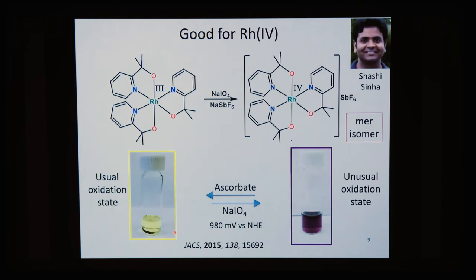And rhodium usually occurs in the rhodium 3 oxidation state. And you can see on the left the yellow color of the rhodium compound with three pyalks. And sodium periodate allows oxidation to the rhodium 4 state, but only for the meridional isomer. And this gives this nice purple color. And it requires quite a high potential, 980 millivolts.